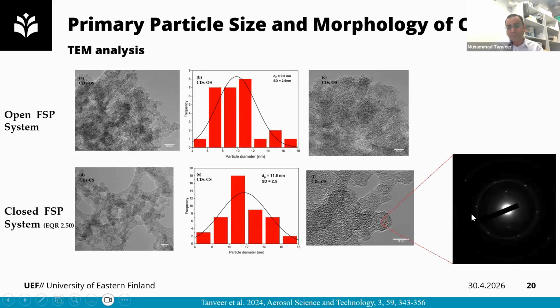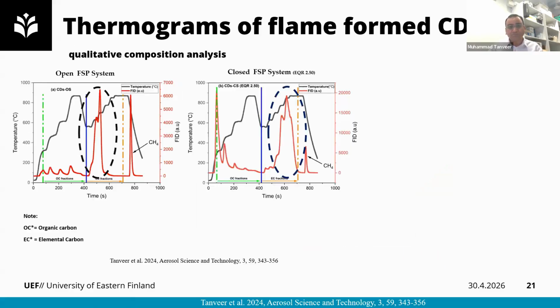Also, we have observed stacking in our TEM diffraction analysis. So you can see here a ring structure with some bright dots. This ring structure is basically carbon dots, and these bright dots are the graphitic carbon on the surface of the carbon dots. Also, we can see that the interlayer spacing is quite large in the case of this particle. This shows that there is quite an interplay between the defect-induced structure and graphitic structure. So it shows a transformation of these structures in the particle.